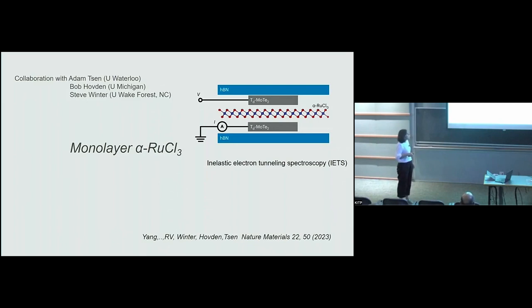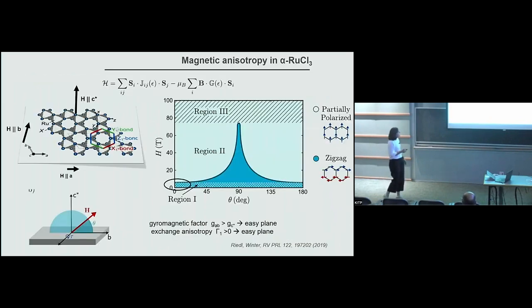And then he measures by contacting this system. He does inelastic electron tunneling spectroscopy. In inelastic electron tunneling spectroscopy, changes in the conductance give you information about possible magnetic excitations in the system. So one thing to remember is that alpha ruthenium trichloride has an important magnetic anisotropy.